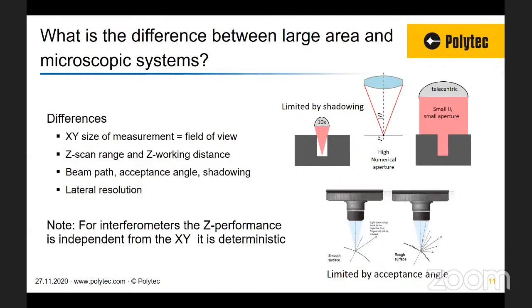Naturally, the microscope systems will handle higher sloping surfaces much better. On smooth surfaces, you could typically get up to maybe 40 degrees. On surfaces with micro-texturing or surface roughness, these values can jump up to 85 degrees. With the macro lens system, you can also get very impressive slope measuring capability. Typically, if you're measuring a mirror, you might be restricted to 2 or 3 degrees on a super finished surface. But if you measure cones with some micro nano texturing, you can easily achieve 60 to 70 degrees of slope.